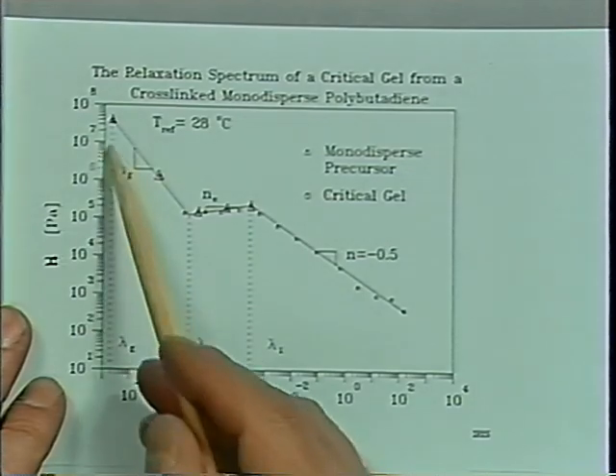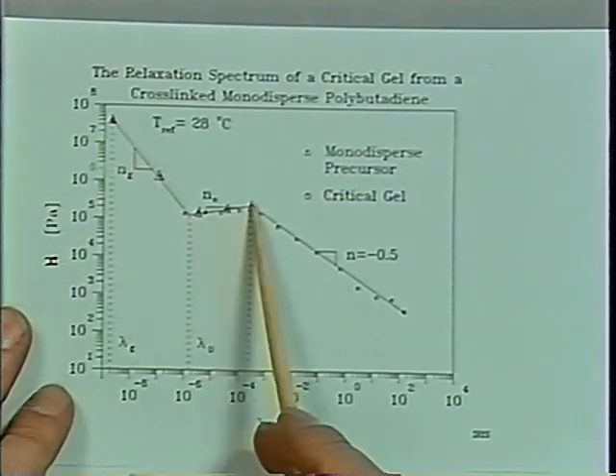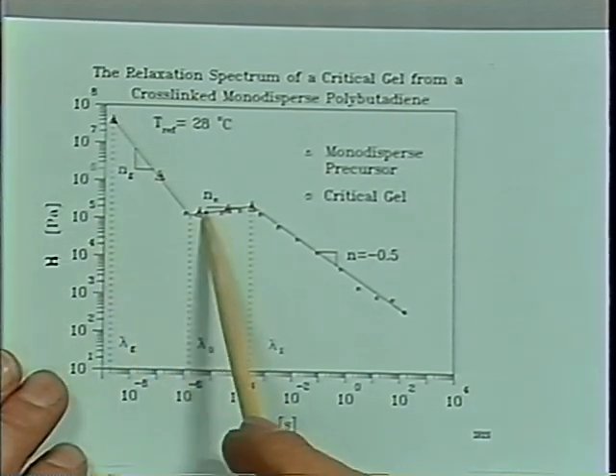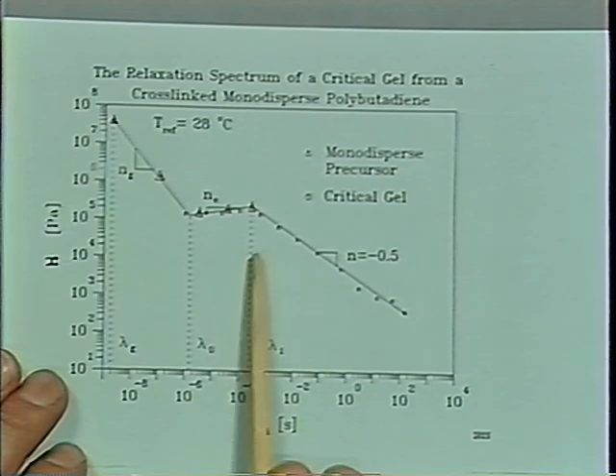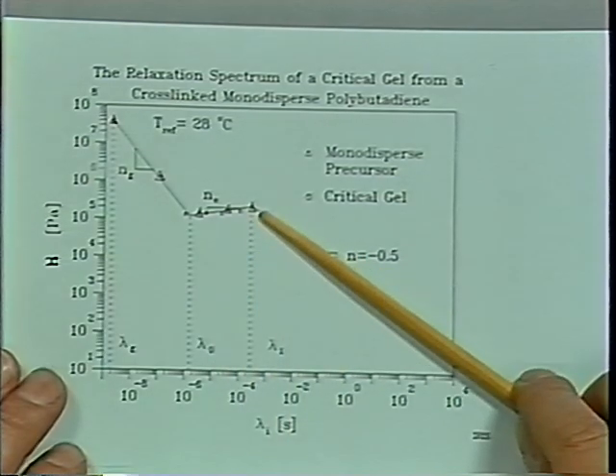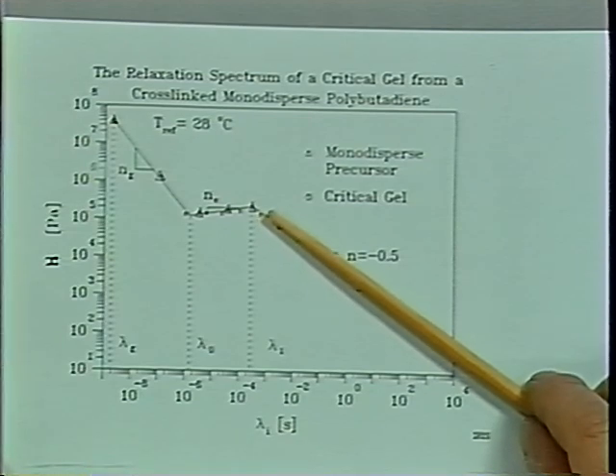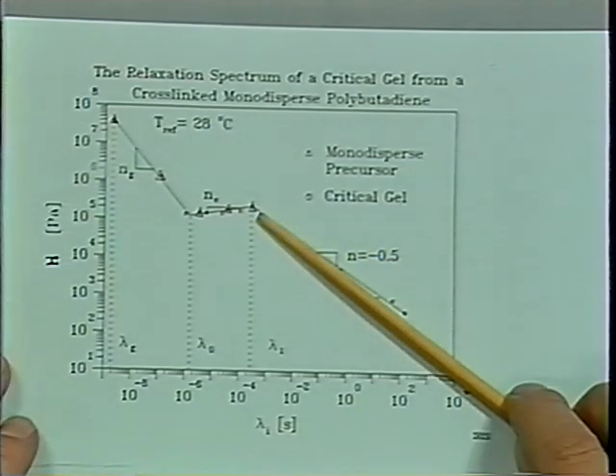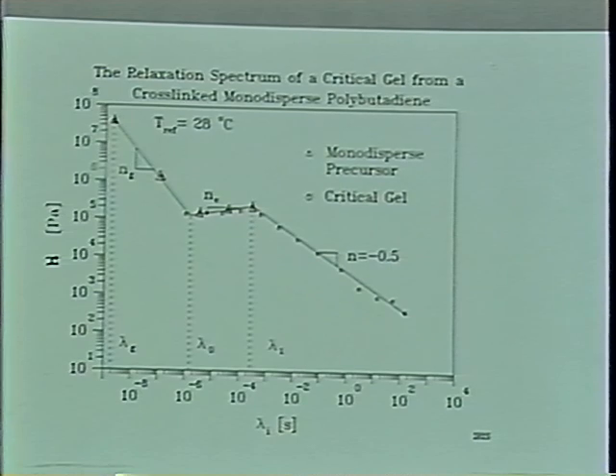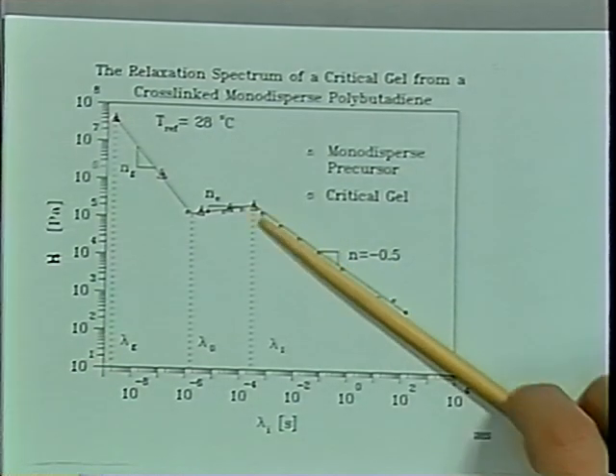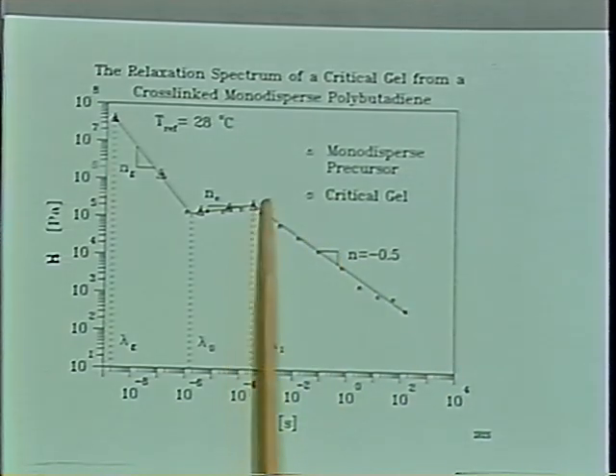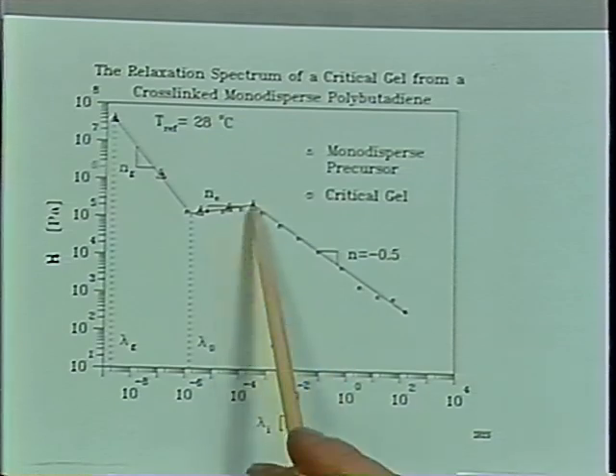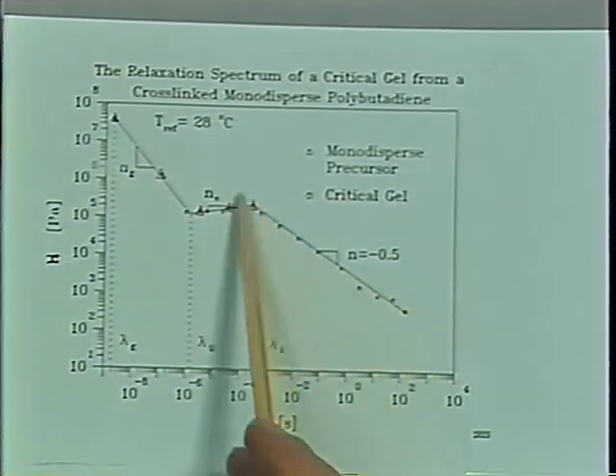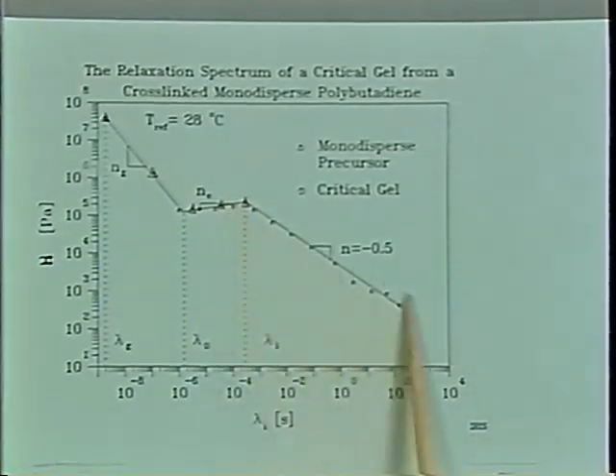The spectrum for this material is drawn here. The initial spectrum is described by the glass transition, and then in the scale here, everything is pushed together with many frequencies. This is the entanglement regime, and then the longest relaxation times are increasing. And at the gel point, it turns out that all the slopes we are finding so far are close to 0.5. I would be hesitant to say that this is a universal material quantity, because all the other exponents are changing between all kinds of values. But for all our vulcanizing systems, we find a slope of 0.5 and this we would describe with the gel equation. This would be the lower limit where entanglement is setting in. We would maybe use a BSW equation for this part, and the gel, the Chambon type spectrum in this range.